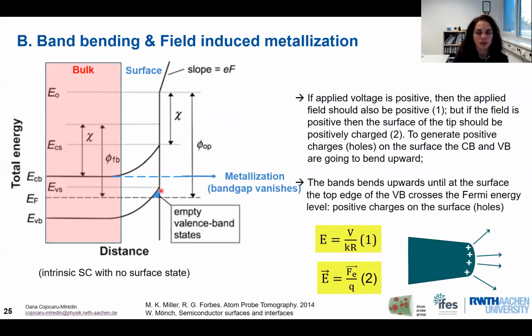Now the metallization point is the point where we bend the valence band on the surface so much that it reaches this point, which is actually where we have the conduction band in the bulk. This is also the point where the Fermi energy level will be more or less sitting in the middle of the valence band on the surface. So this is how it is explained that on the surface of the atom probe tip, if we bend the valence band and the conduction band so much, we get a metallic surface.